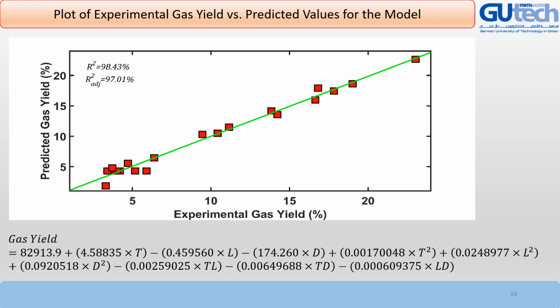Plot of experimental gas yield versus predicted values is shown in this slide. As you see, the R squared of 98.43 and adjusted R squared of 97 show a very good fitting of the data on the model. The model for gas yield is also shown at the bottom of the slide.